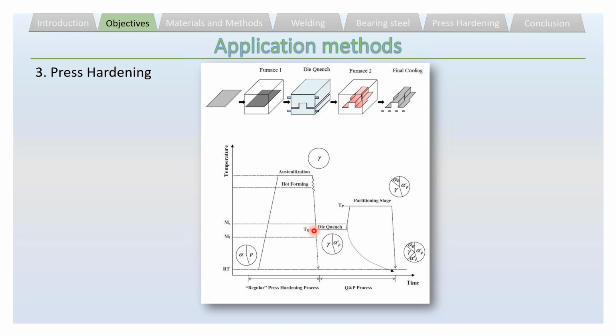But if we combine quenching and partitioning with hot stamping, you can see this. It means that after hot forming, we can quench in a die quench, which is set at a specific temperature that we want as TQ, and then we can take the sample out of the die quench to the second furnace. In the second furnace, we can apply the higher temperature of partitioning, and then final cooling.